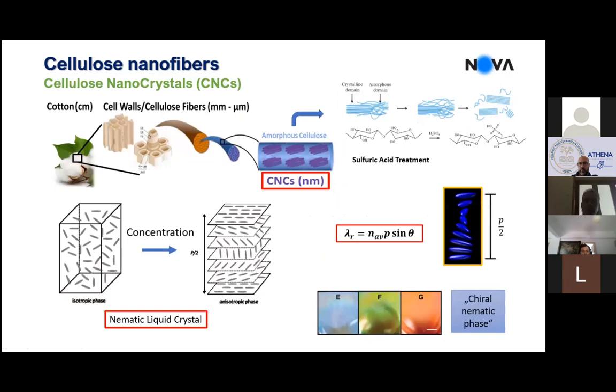We can go further down in dimension to the nanofibers and extract just the crystalline part of these fibers. If you look at a nanofiber of cellulose, you have what we call crystalline domains, and amorphous domains, which are regions on the fibers where the cellulose chains are not well organized in terms of structure. You can get rid of this amorphous domain and keep just the crystalline domain by a selective dissolution in an acid, and you get what we call cellulose nanocrystals. These cellulose nanocrystals have a very interesting characteristic.